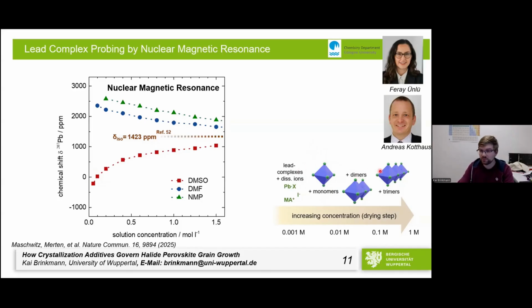And the further we go towards these larger colloids, the more we go towards a solid-state perovskite-like species, or colloid-ish species, that we have in the solution. And this actually fits quite nicely with the solid-state NMR. If you do a solid-state NMR, you end up with 1423 ppm, which is the chemical shift in the NMR, and it's almost perfectly in the middle between there. So the asymptote, or the seeming asymptote that we have here, basically looks like it's passing through towards the solid-state NMR. So far we're happy.